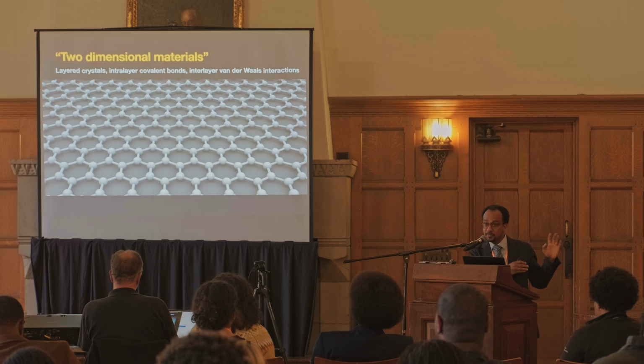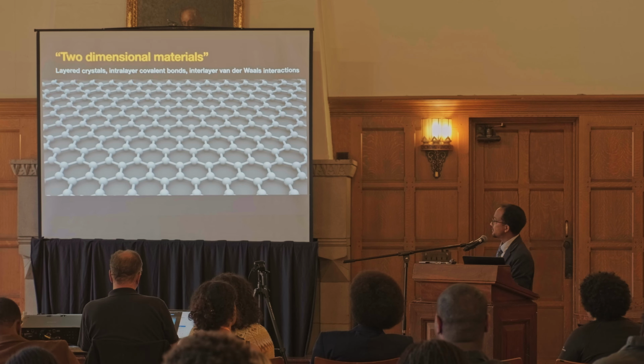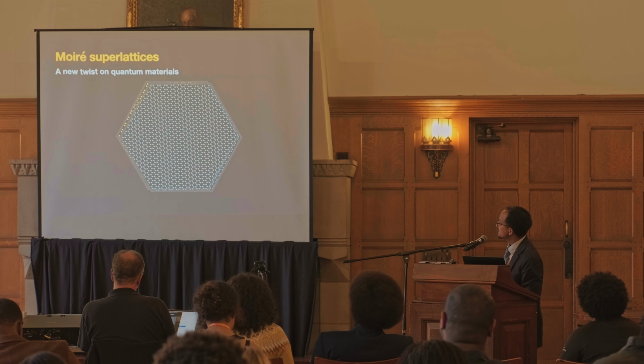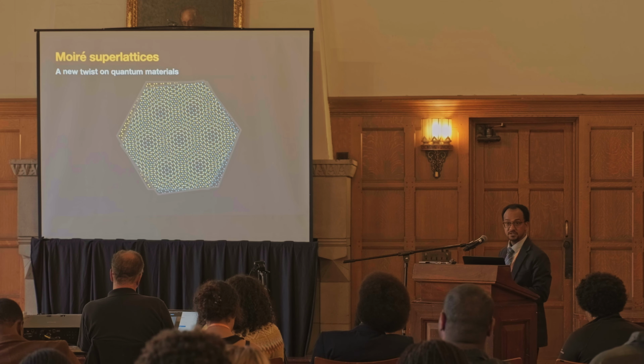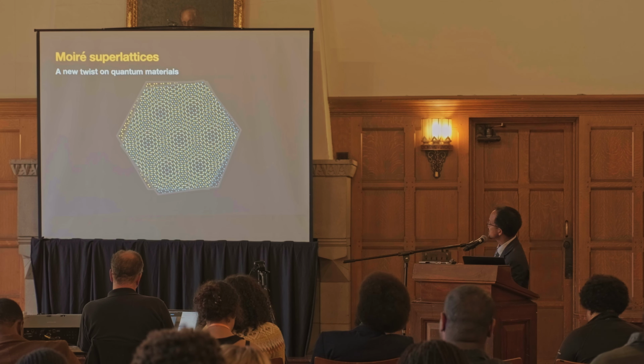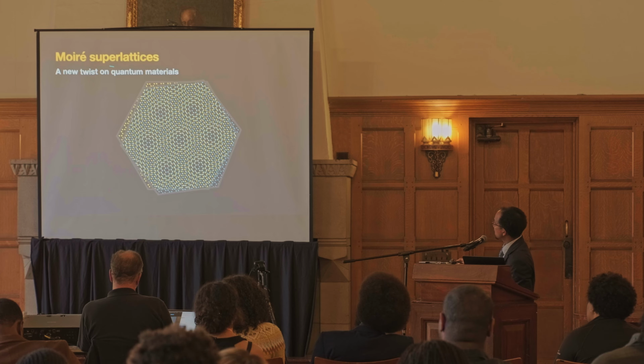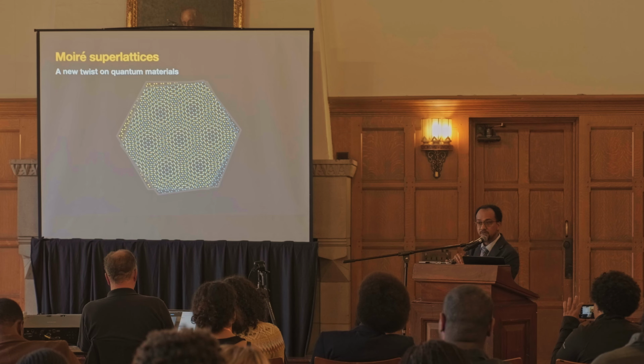Going back to these 2-dimensional materials I talked about, with graphene as one example, usually electrons in graphene do not interact with each other at all. They don't really see each other, and so that's why they're able to move without scattering, as if they have no mass. A very interesting thing happens when you take 2 layers of graphene and stack them with a twist. You take 2 layers of these carbon atoms, stack them with some rotational offset, and you create this Moiré superlattice, which is simply a modulation in how the atoms are arranged on each other locally.